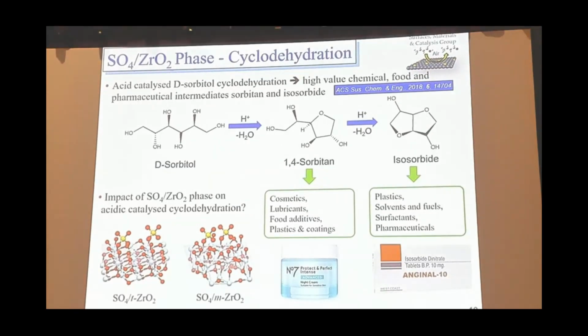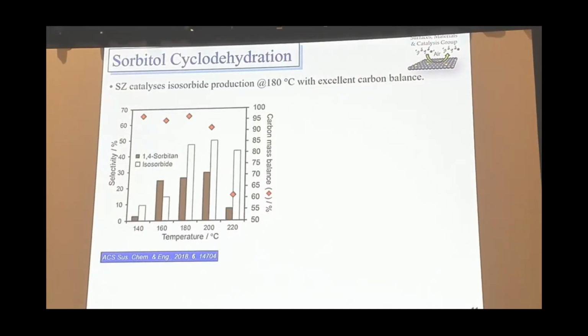So again, thinking about the acid-catalyzed reaction, we've looked at sulfated zirconia for these systems. And in this case, what we decided to do was look at the impact of the zirconia phase on the catalyst performance. So here we've taken tetragonal zirconia and sulfated it, or we've taken monoclinic zirconia and sulfated that. And we find if you get a different distribution of sulfate groups, that affects their acid strength and also their activity. So if you look at the performance of the standard sulfated zirconia just as a function of temperature, you can see that the isosorbide and sorbitan yields increase as a function of temperature.